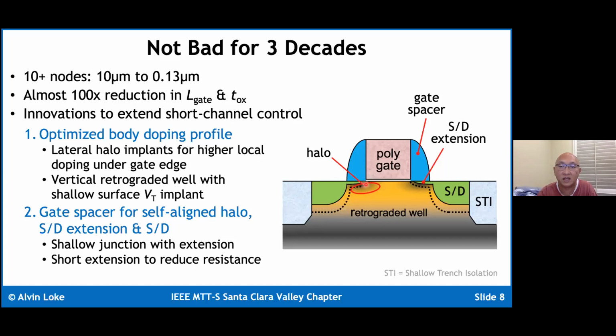But then we basically need to compromise, not have the series resistance of the transistors, the access resistance, being too large. Otherwise, you get significant short source degeneration. And by having the spacers self-aligning the source drain contact regions with a much thicker and deeper source drain region to have lower source drain resistance or diffusion resistance, allows you to recover some device performance.